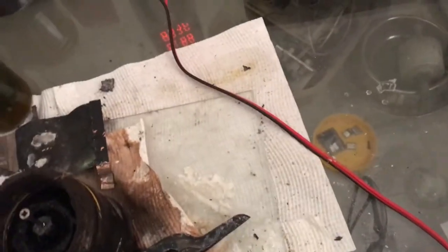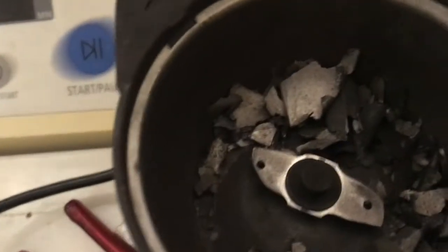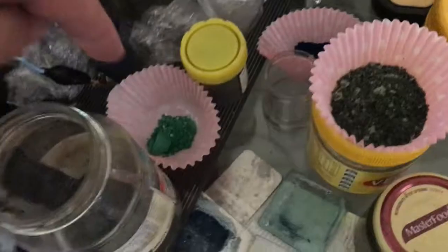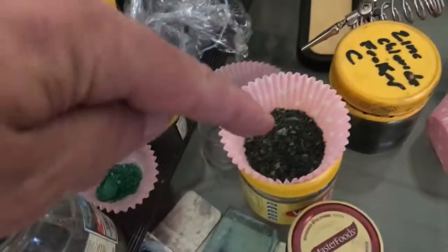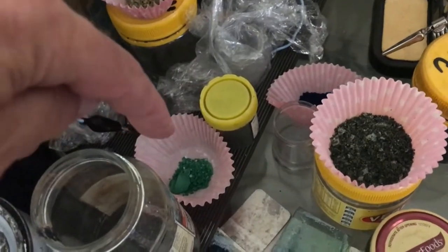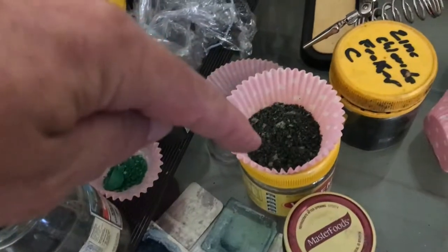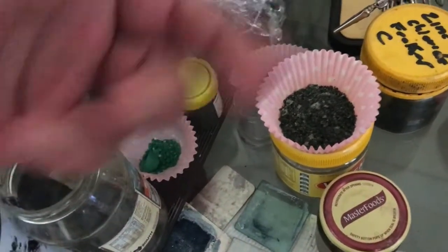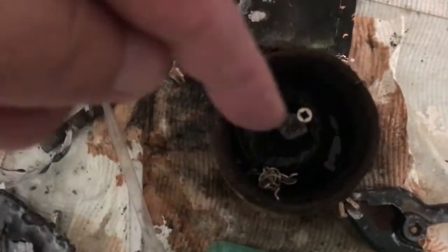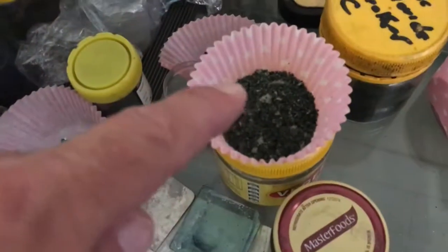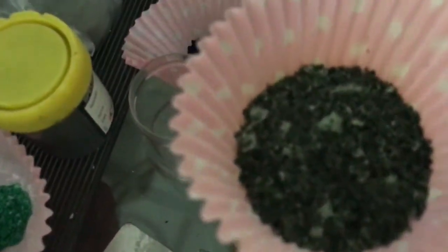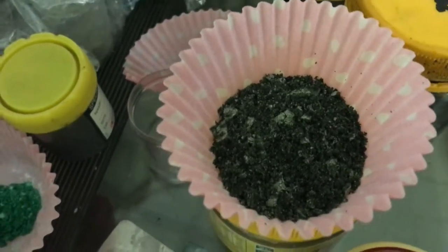And what's left of our nickel, there's not a lot, but that did 2 plates really. The first one failed, as I showed you those flakes, which I might crush up and also stick in as nickel flakes into the mix. So there's 5 grams left in that batch, which is a pure batch. Normally a pure batch gives you 10 grams of nickel hydroxide. This was the batch I made, and that probably would have had 10 grams as well, plus the bits of the round carbon cylinders that broke off as I was submerging them. So I'll weigh that up and then we'll get a measurement of how much carbon could be in there.